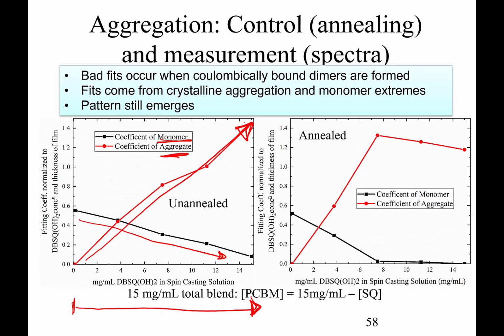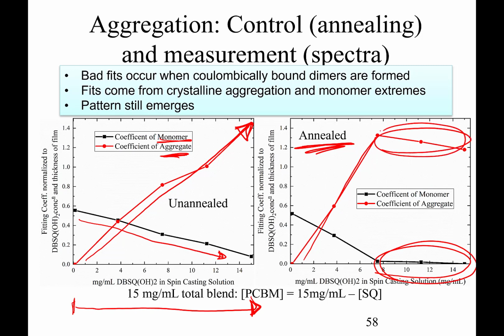However, when it comes to the annealed samples, what we find is that actually the amount of monomer drops pretty much to 0 at about 50% of Squaraine in the film, and what we also find is that the amount of aggregate in the annealed form jumps more or less up to 100%, almost all aggregate at about 50% of the sample. So this pattern nevertheless emerges that beyond about 50% Squaraine, we pretty much get 0 monomer and more or less 100% aggregate. There's some mixture with the unannealed samples.